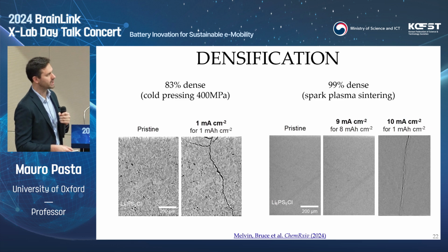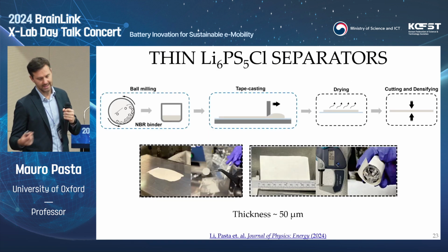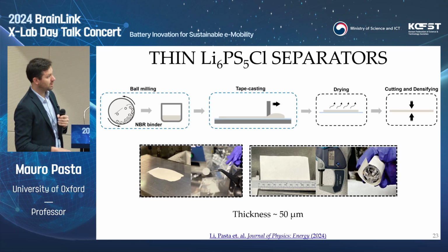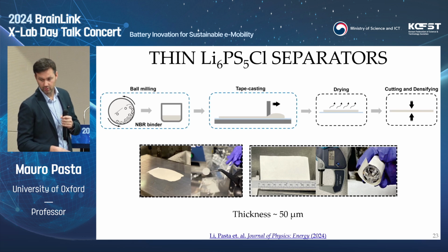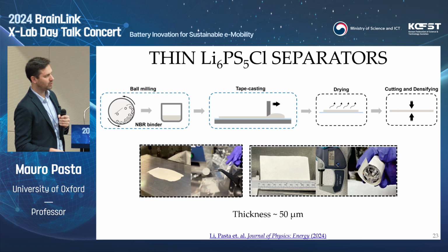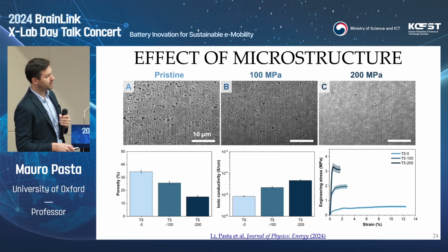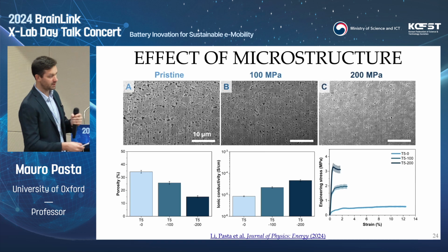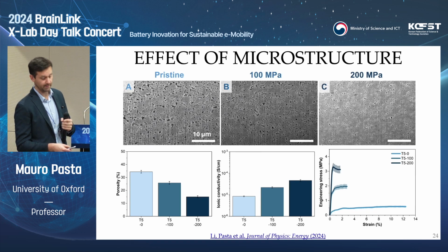Now the fundamental question is, how do we achieve this level of density in something a little bit more pragmatic and practical, like a thin film separator? And that's a whole field of research that we're still carrying out and pursuing. You can tape cast quite thin solid electrolyte layers right now. It's not that difficult. If you add a tiny bit of binder in there, you can tape cast it quite easily, below 50 microns. Quite flexible still because they're quite porous. But as you can see over here, even if you apply higher pressure, you still retain quite a bit of porosity. So you do increase conductivity as you densify these films. You do increase engineering stress, but still the presence of all this porosity results in very low fracture toughness, and therefore they pretty much all short at a very low critical current density. So here again, understanding densification in detail and the whole science of densification will be critical.